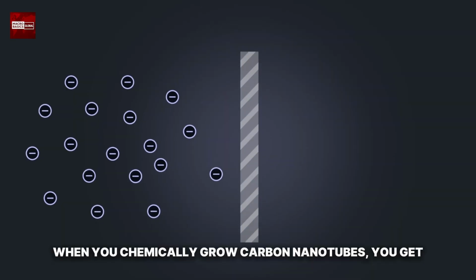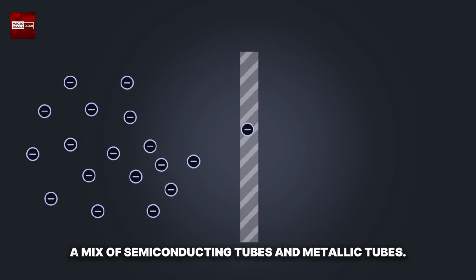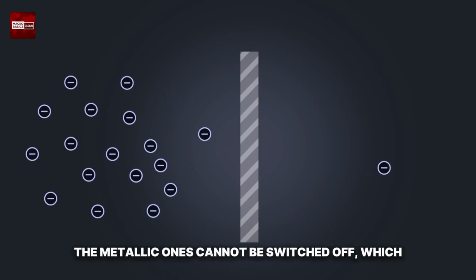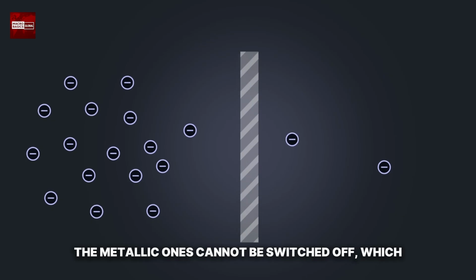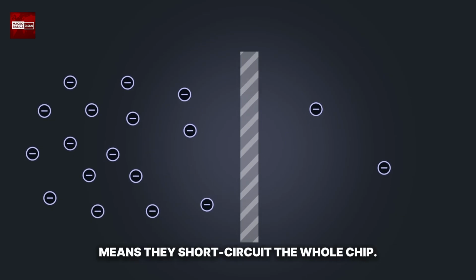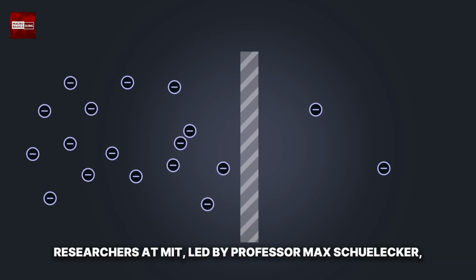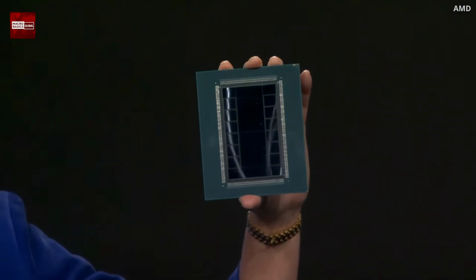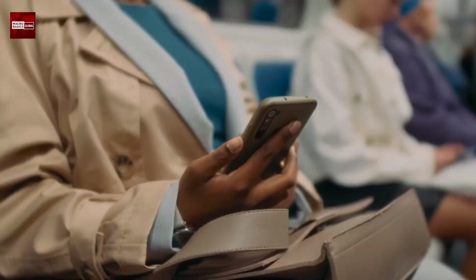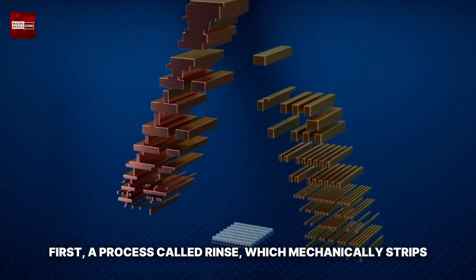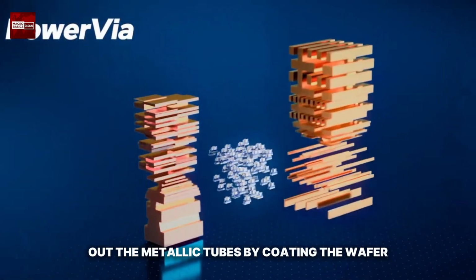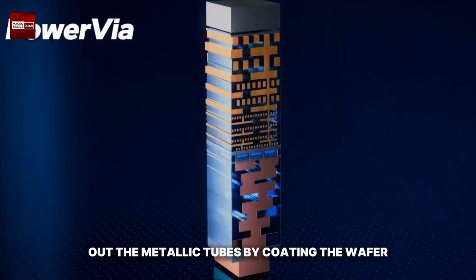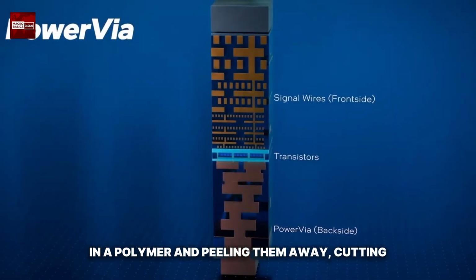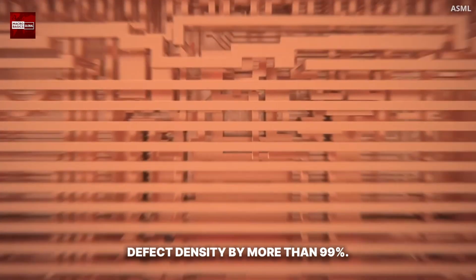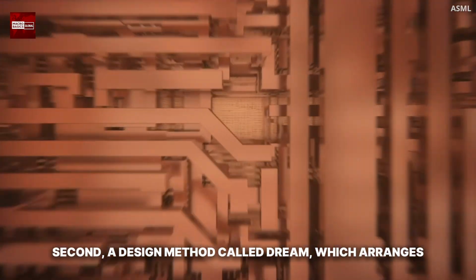When you chemically grow carbon nanotubes, you get a mix of semiconducting tubes and metallic tubes. The metallic ones cannot be switched off, which means they short-circuit the whole chip. Researchers at MIT, led by Professor Max Shulaker, solved this with 2 clever fixes. First, a process called RINSE, which mechanically strips out the metallic tubes by coating the wafer in a polymer and peeling them away, cutting defect density by more than 99%.